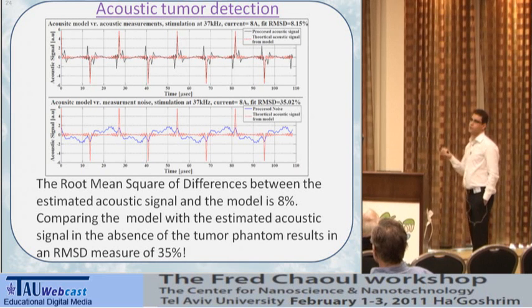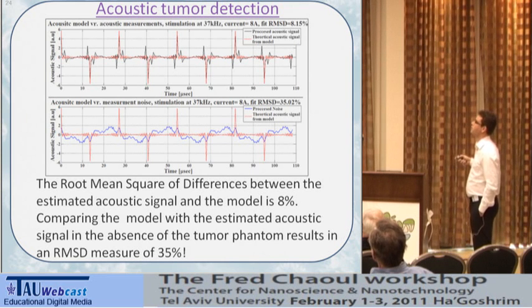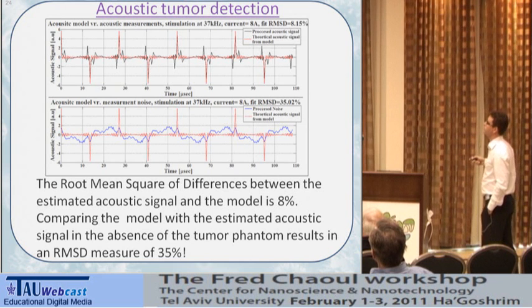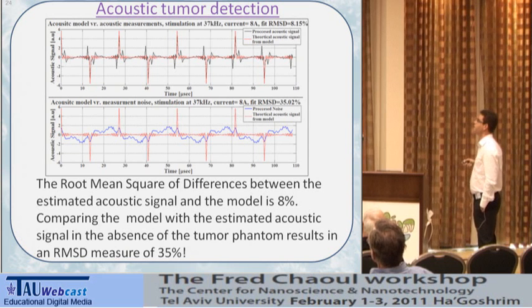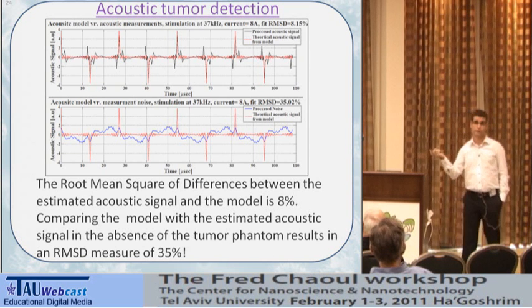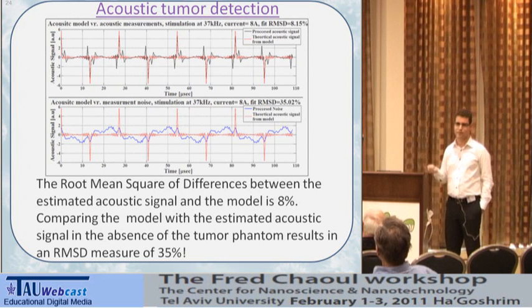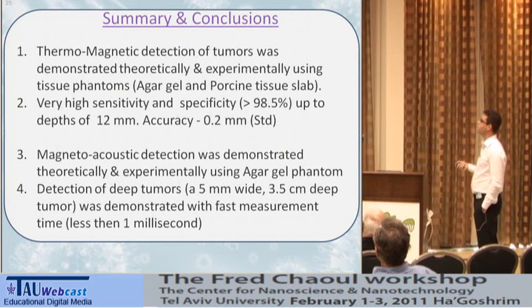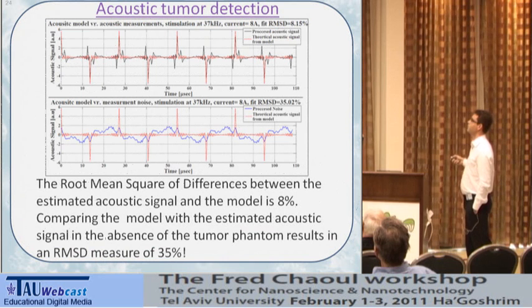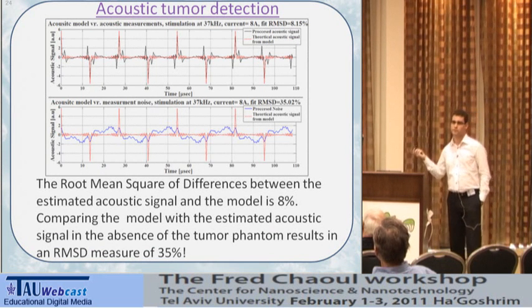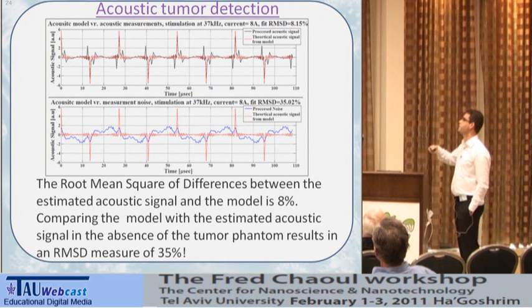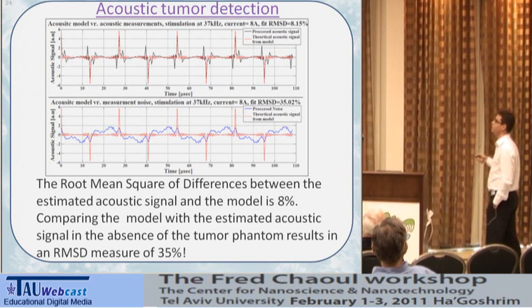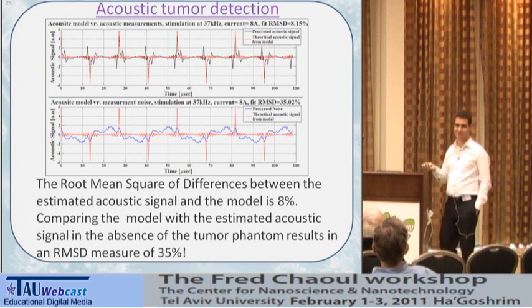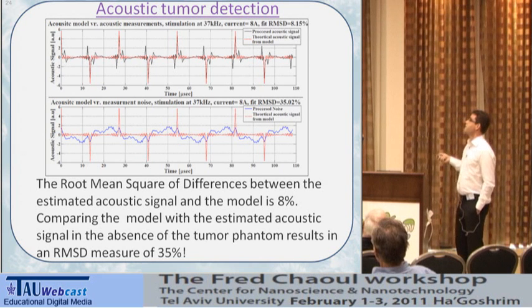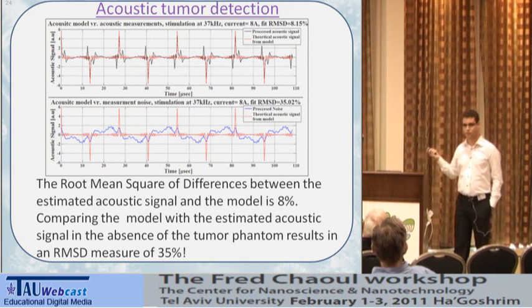we compared it to a situation without the tumor. As you can see here, in red is our simulation, the model, versus the true measurement, and you see it correlates very nicely. And here we took a situation without a tumor. We did the same signal processing algorithm, the same subtraction, everything. And you see just residual noise. It doesn't look like our model at all. So it's very, very simple to see whether there's a tumor present or not. You just need to correlate with the model and threshold the correlation at some point. This was done for a 3.5 centimeter deep tumor, which is quite nice.